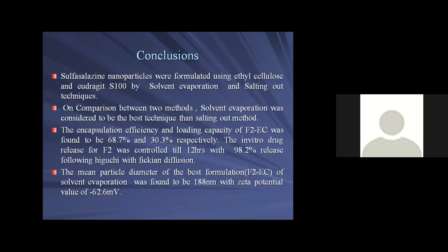So both techniques are considered to be good techniques for the preparation of sulfasalazine nanoparticles. Comparatively, in the solvent evaporation method, we obtained a mean particle diameter of less than 200 nanometers. Normally, what we would like to achieve is a formulation with less than 200 nanometers, more than 80% entrapment efficiency, showing 100% drug release in more than 12 hours, which is considered the best one.